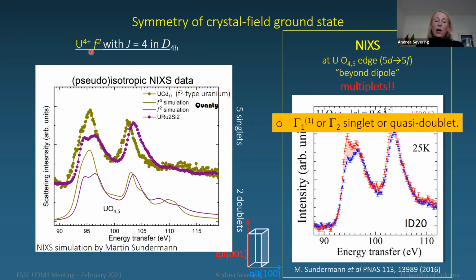In case you're wondering why I'm only comparing it here with the ground state symmetries of a uranium 4+, f2 configuration, then please look at these pseudo-isotropic data. They were constructed from the different directional dependent data. The uranium ruthenium 2 silicon 2 is here, the purple data. And then the uranium cadmium 11, which is sort of an f3 type intermetallic uranium compound, has a very different line shape. And we can model it. Here, Martin Sundermann did the simulations, and we can model the uranium ruthenium 2 silicon 2 isotropic data very well with an f2 configuration and the uranium cadmium 11 with an f3. So we really can distinguish very well.